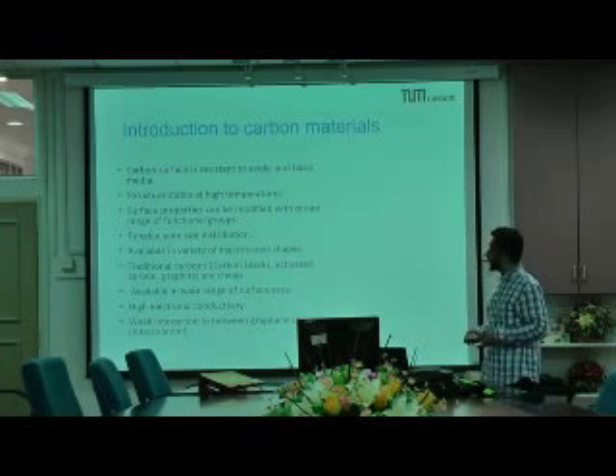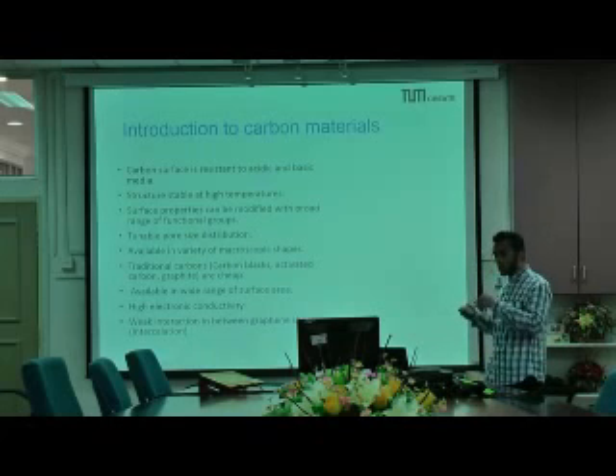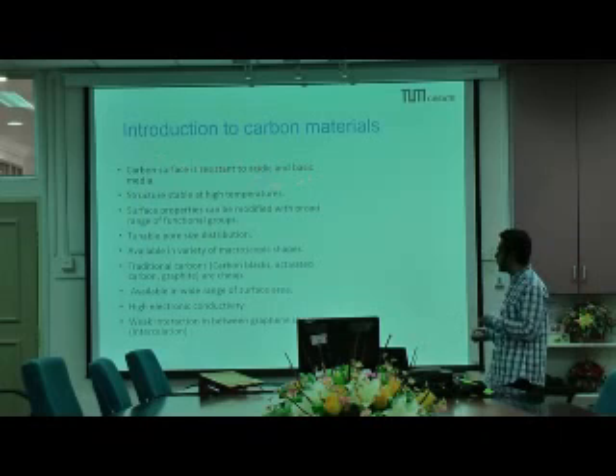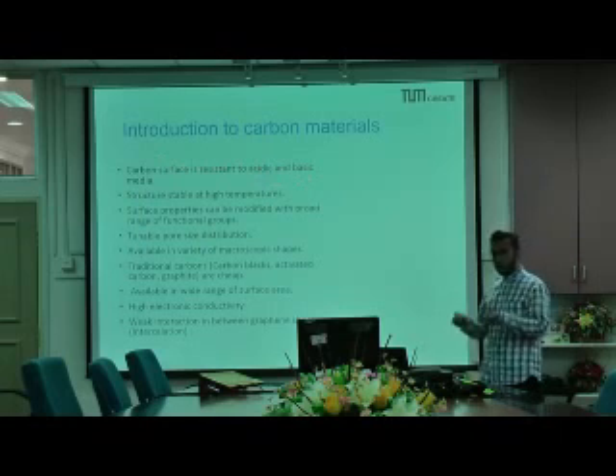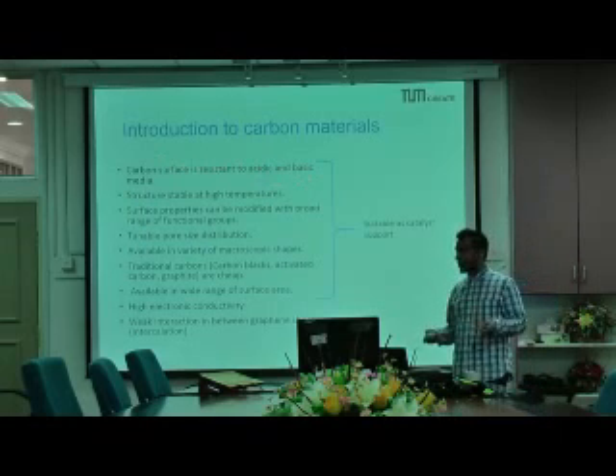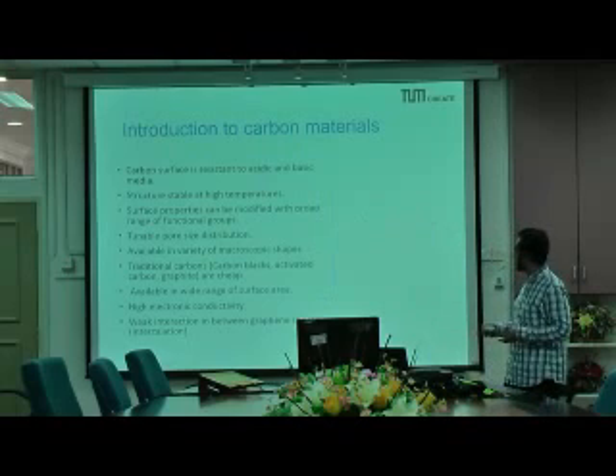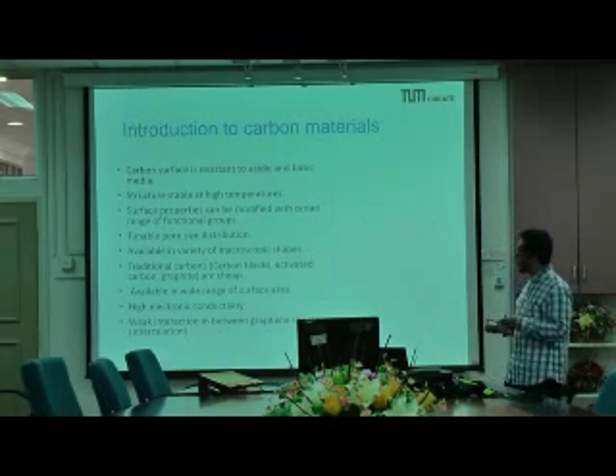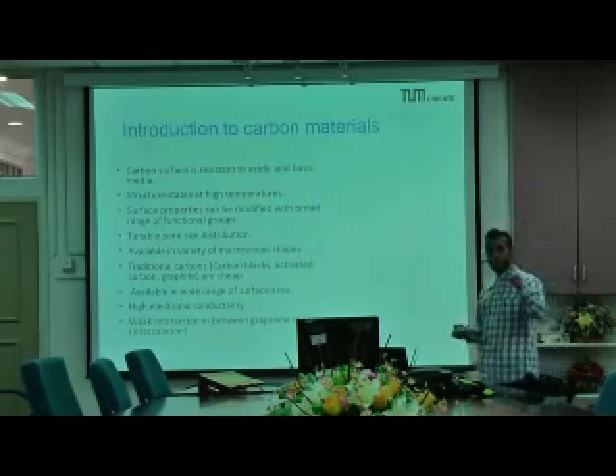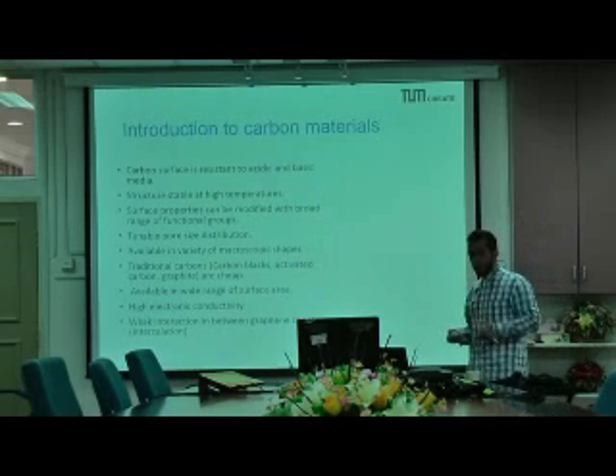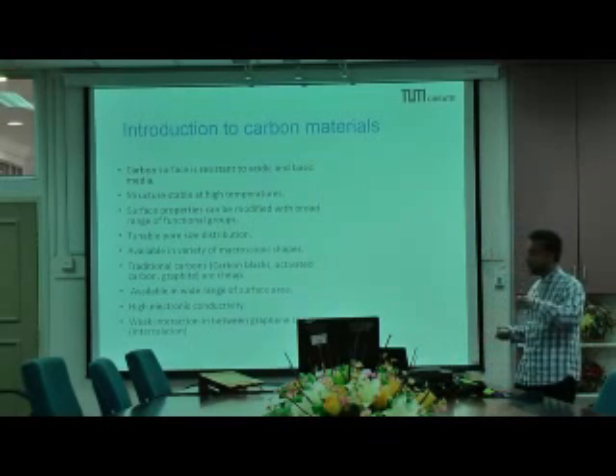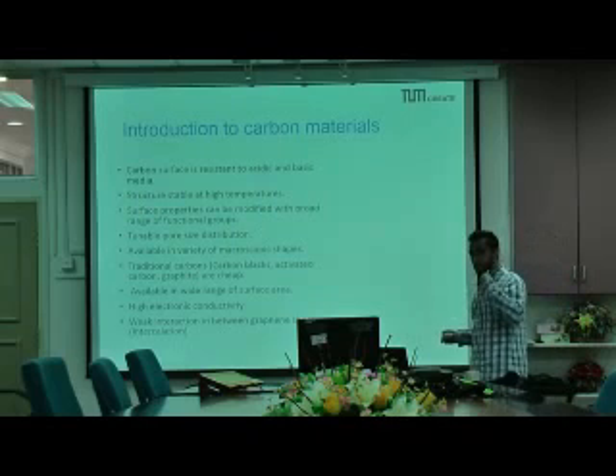Other types of application. The main property of carbon is that it's resistant to acid and basic media. If you anneal it at high temperature, it wouldn't get destroyed or collapse. It's very stable. And you can modify the surface properties by introducing functional groups or changing the microstructure from sp2 to sp3. And you can change the wetting properties, the zeta potential of the materials.